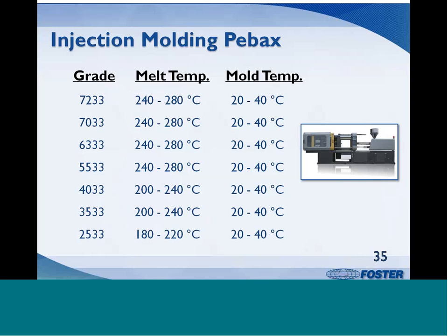This chart shows the suggested temperature ranges for molding Pebax. There is a direct relationship between hardness and injection molding temperatures. The harder, more crystalline grades require more heat to achieve the desired melt viscosity.